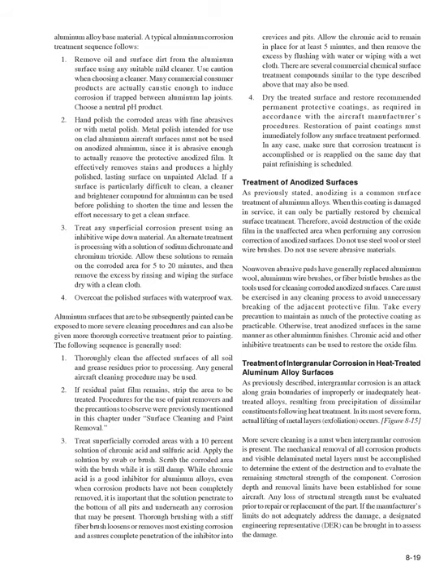While chromic acid is a good inhibitor for aluminum alloys, even when corrosion products have not been completely removed, it is important that the solution penetrate to the bottom of all pits and underneath any corrosion that may be present. Thorough brushing with a stiff fiber brush loosens or removes most existing corrosion and assures complete penetration of the inhibitor into crevices and pits. Allow the chromic acid to remain in place for at least 5 minutes, and then remove the excess by flushing with water or wiping with a wet cloth. There are several commercial chemical surface treatment compounds similar to the type described above that may also be used.